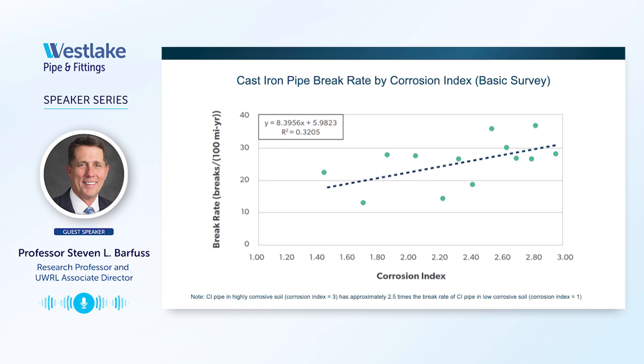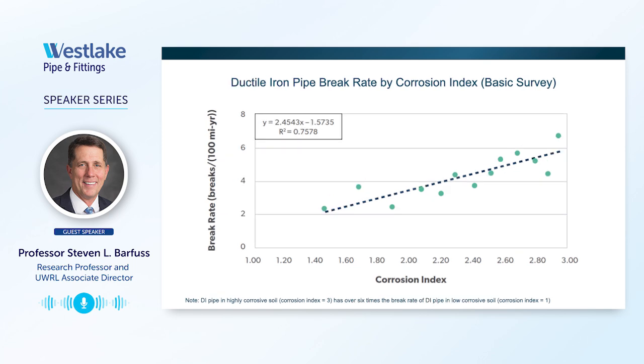So here's corrosion index on the x-axis. Here's a 3, meaning highly corrosive soils, 2, medium, and 1 being low corrosive soils. And you can see right here, this 3 down to a 1, that's approximately 2.5 times more breaks with highly corrosive soils than low corrosive soils. That's what we can capture out of this graphic. Same for ductile iron. We can see that there's over 6 times the break rate of ductile iron pipe in highly corrosive soils as opposed to low corrosive soils down here where the intersect is. And a fairly good R-squared for this linear regression.